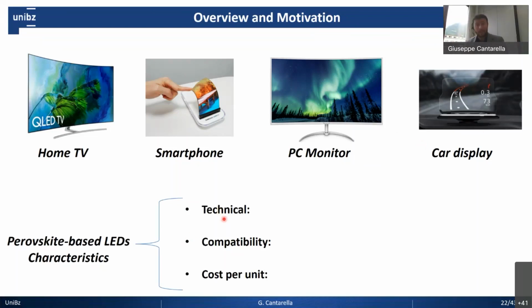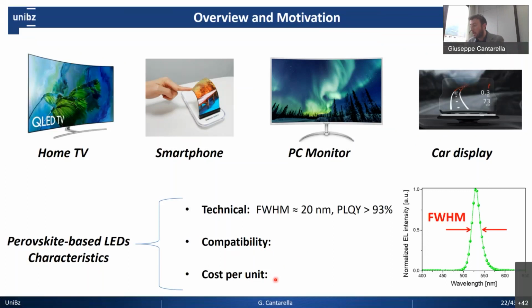Three ways to judge these are the technical features, so the results that we can get, the compatibility with respect to other technologies, so how easy or how difficult it is to combine perovskite LED with other thin film technology, and clearly, if we would like to reach the market, the cost per unit, so how much a single LED would be. Just going one by one, clearly there are advantages in using perovskite because they have a full width at half maximum, as you can see here in this plot, which is as low as 20 nanometers, so much smaller than what could be achieved with other technology. And also the photoluminescence is above 93%. So clearly there is a great advantage in using this technology rather than others.